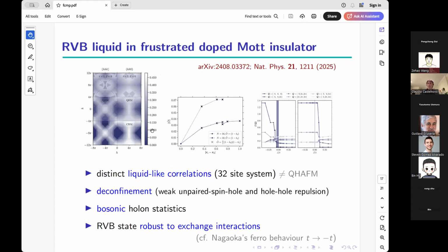We did the same system for a Heisenberg antiferromagnet, a quantum one, QHAFM, and a classical one, CHM. And these are the HHK plane and HK0 plane, which are typical ones people look at. What one should take from this is A, don't look at it too seriously. B, we don't see sharp features consistent with the liquid nature. And D, or C, they don't look immediately like a Heisenberg antiferromagnet. So it seems that maybe the correlations are a little bit different, but really it's too small of a system size